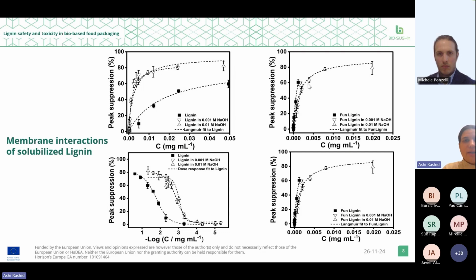In the top plot, the data is fitted to the Langmuir adsorption isotherm, and we got a very good fit. So interaction of both lignins, uncoated and functionalized coated lignin, with the biomembrane sensor follows the Langmuir behavior, where the interactions increase with increasing concentration of the lignin until the saturation point is reached.